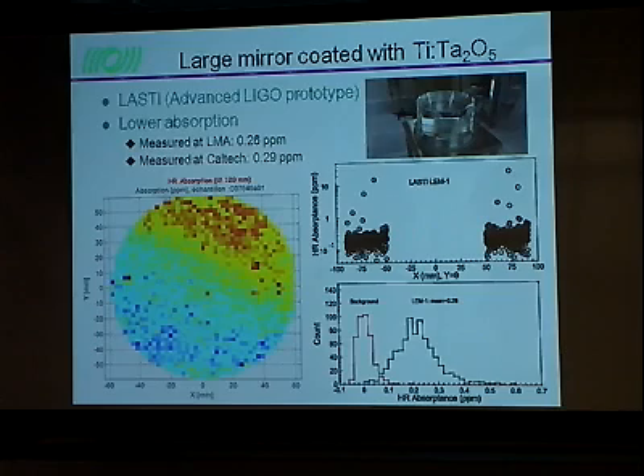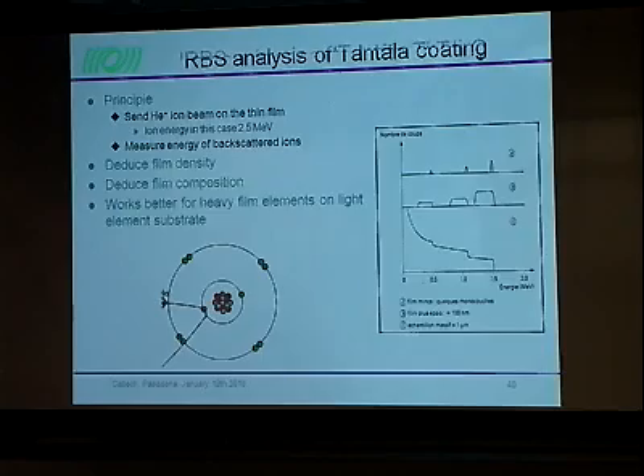Actually, the first version of this material was used to coat one of the Advanced LIGO Pathfinder mirrors, the so-called LASTI mirror, and losses in that case were measured at the level of 0.3 ppm or less, both measured at LMA and here at Caltech. So it is the best material we have.